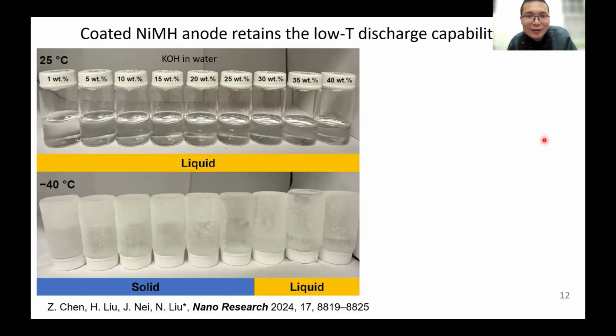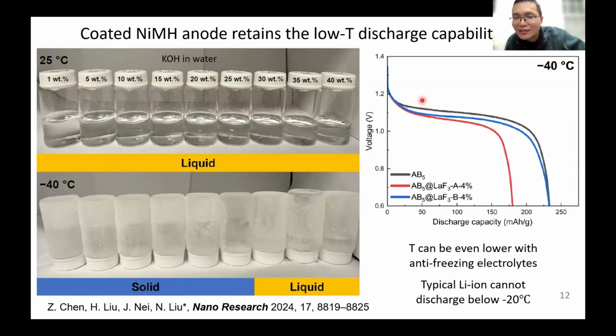So we did the low temperature discharge capability testing. First, I want to show you this picture. At -40 degrees C, if you have a high concentration of KOH in water, the solution can maintain its liquid state. You turn these vials over and the liquid comes down. The lower concentrations of KOH all freeze, but the high concentration one can maintain its liquid state. And then we did the discharge at this low temperature in this liquid electrolyte.